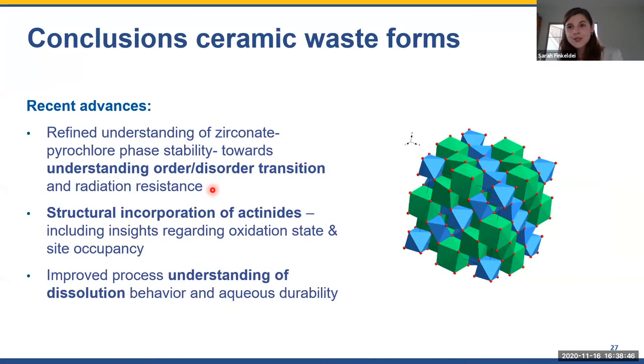Okay, so to sum this part up of my talk, I showed you that we are looking at these order-disorder transitions, which we are expecting as a result of self-irradiation of potential nuclear waste forms for zirconate-based pyrochlores. We can actually structurally incorporate actinides, plutonium and curium. It's the A site of these pyrochlore samples.